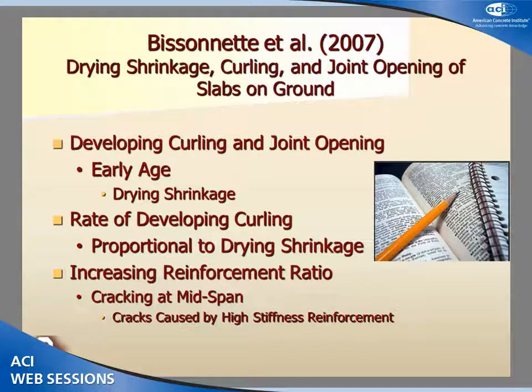In 2007, Bissonnette and his group studied drying shrinkage, curling, and joint opening of slabs on ground, and they showed that the curling and joint opening occur at early age, and they relate to drying shrinkage. In other words, they said that the rate of developing curling is proportional to the drying shrinkage. They also found that when they increased the reinforcement in the slabs, they noticed cracks at midspan. So they concluded that high stiffness reinforcement can cause cracks in the slab.